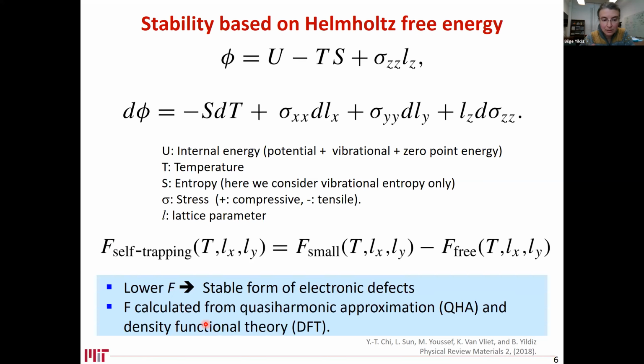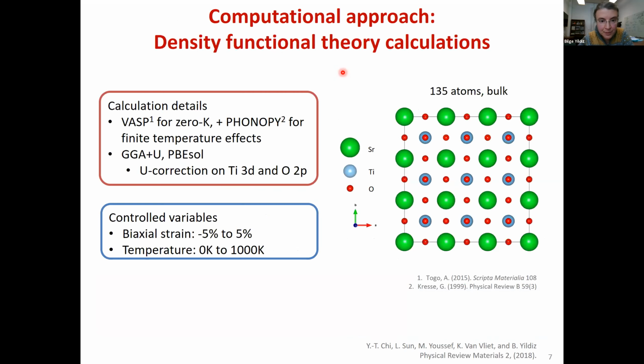And again, we rely in part on density functional theory calculations, but also on quasi-harmonic approximation calculations to introduce finite temperature effects, in particular coupling to the internal energy and vibrational entropies. And the codes that we use for these calculations are VASP, which is a very widely used first principles based tool, and PHONOPY, which allows us to introduce the finite temperature effects. And we are looking at a temperature range from very low to 1000 Kelvin, as well as a strain range going from minus few to plus few percent biaxial strain,